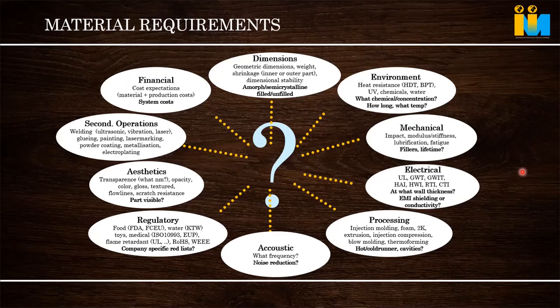In the headlamp of a car, it has to be made in polycarbonate because it has higher impact strength, and it has very good see-through clarity and light transmission. But when the car is moving at higher speed, even small dust hitting the headlamp can make scratches on that area. So to avoid that, a secondary operation, hard coating, like silica hard coating. That coating is so hard that it will not allow the particles to touch the plastic. So a thin layer of UV-cut hard coating will be done.